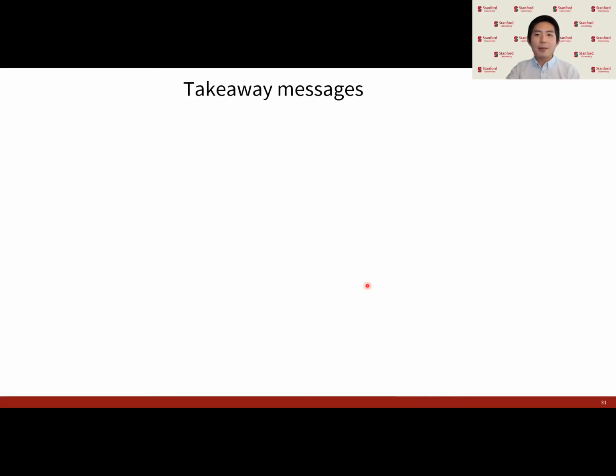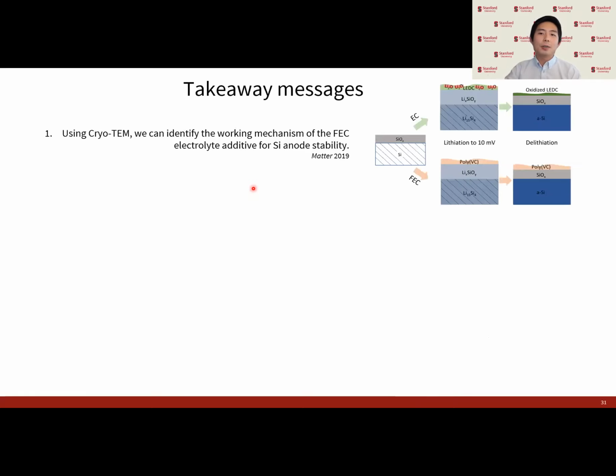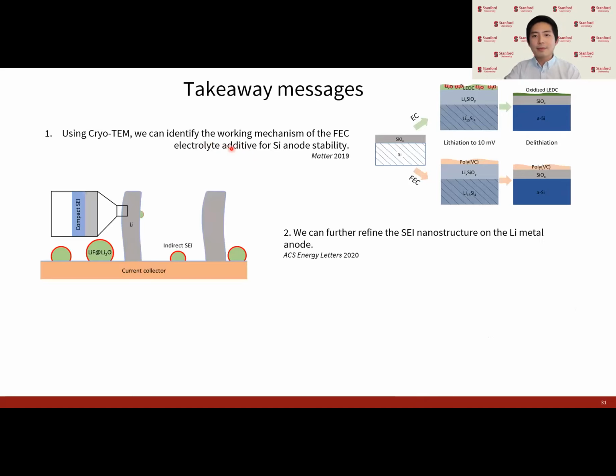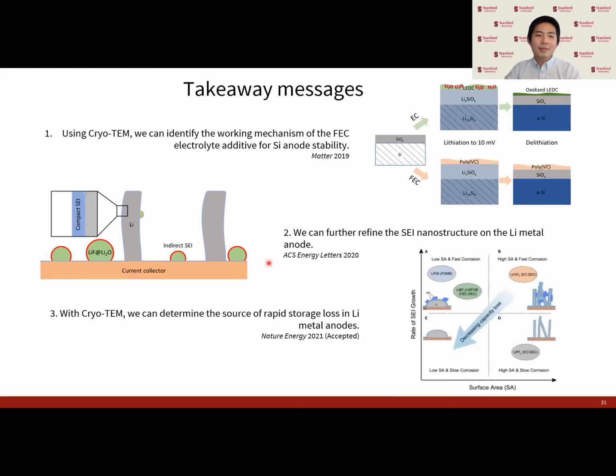And basically, just to recap everything we've seen today, I've used cryo-TEM to identify how FEC stabilizes the silicon anode. And then I showed how cryo-STEM can give new insight into the real SEI structure, and how classic characterization methods like XPS can give you completely wrong results if you're interested in what the SEI actually looks like. And finally, with cryo-TEM, we can identify the source of this rapid storage loss in lithium metal anodes.